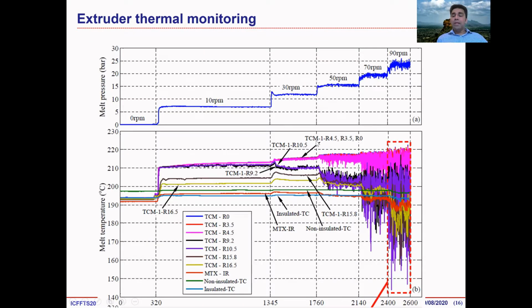This is another comparison of different temperature sensors. Here, all of these measurements are from the thermocouple mesh at different radial locations across the melt flow. You could see they capture really high dynamics, or high variations, of melt temperature. While the thermocouple mesh is capturing really huge temperature fluctuations, the infrared sensor, this red signal, captures some dynamics. It can follow the thermocouple mesh, but it cannot pick up the magnitudes of the variations.